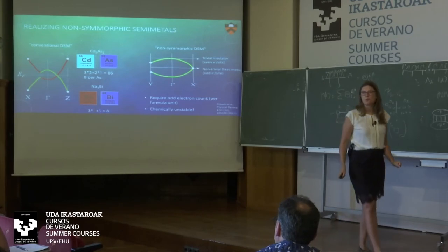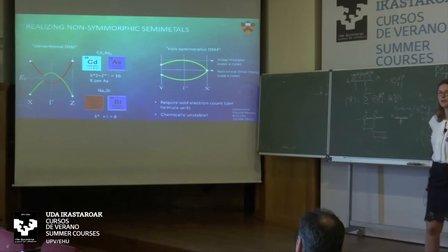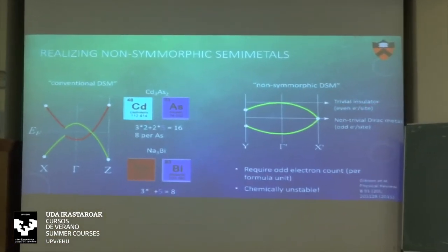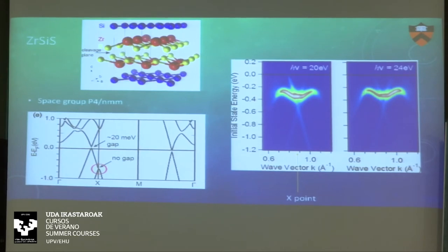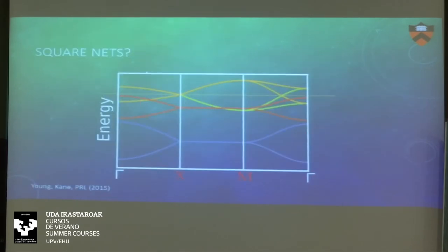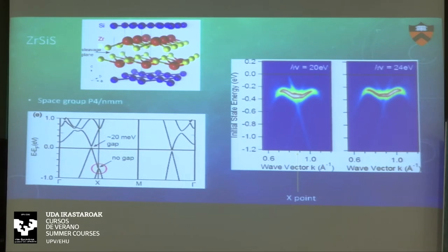We had confirmed this has the electronic structure we wanted. There's also a table of materials listed in the ICSD that are isoelectronic and isostructural — most of the ones at least at the top have now been shown to have the same kind of electronic structure. Going back to non-symmorphic materials: the square nets might also be a good candidate for non-symmorphic crossings. If we look at the band structure of ZrSiS again, the band crossing at X predicted in tight binding to be at the Fermi level is actually about half an eV below and above it, and the crossing that was below in tight binding has moved up to the Fermi level. The reason is that the tight binding was modeled on a simple square net, but in reality it's a 3D crystal with three-dimensional interactions that shift the bands a little.